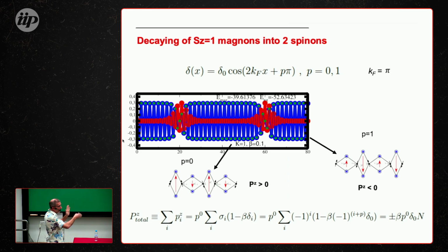And in the other region, when you have the other ground state, because these spinons are domain walls that separate the two ground states, here you get the other deformation, shifted by one. Now the guys which were getting larger here are getting shorter, so now we have a PZ pointing down. Okay, so this is the twofold degeneracy that you had at the beginning that now comes into the game in this excited or one-magnon state. And this will happen with one magnon or any number of magnons. And then what you can conclude is that if you compute P in this system, this area with this area will cancel out and P goes to 0. Okay, so this is the argument.